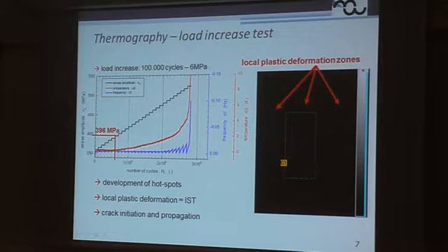So the first tests we conducted were a so-called load increase test, just to try the material and have a look at what's happening, what we can observe on the surface of the specimen. We are starting our load increase tests at a stress amplitude where the material behaves purely elastic, and then we are increasing the stress amplitude after every 100,000 cycles by 6 megapascal. As feedback signals, we chose on one hand the blue curve here, which represents the change of resonance frequency, and on the other hand, the red line represents the change of temperature measured by the thermography camera.